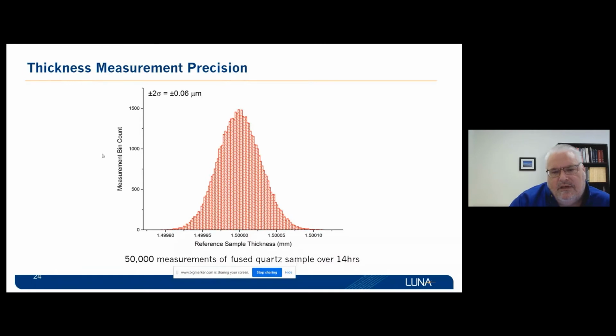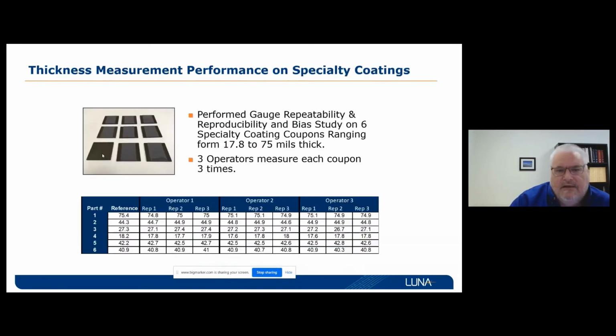Again, this is just showing how repeatable this is. As you can see, this is in microns of variation, not tens of microns of variation. We have 50,000 measurements of fused quartz. Of course, if you're actually measuring real product, there's far more variation from point to point due to orange peel thickness variations under the spray.